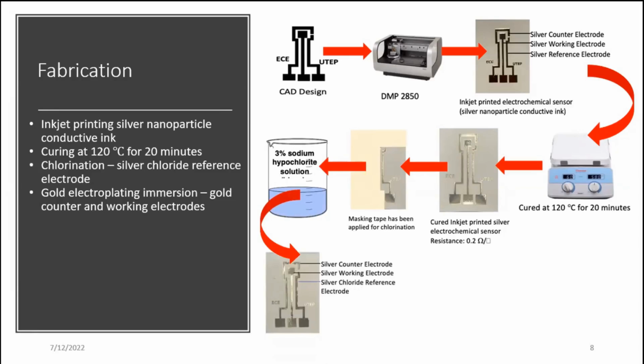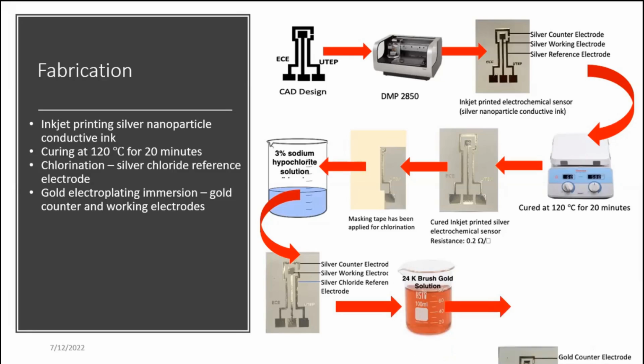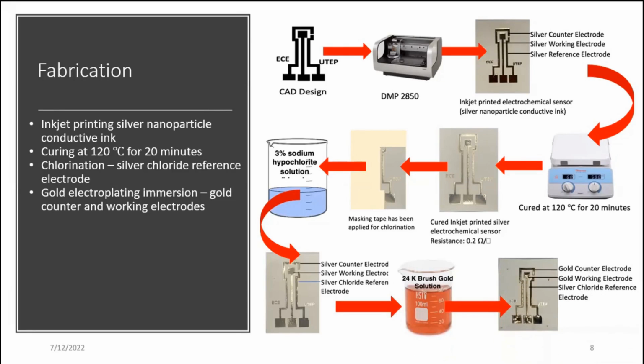And after that, here I want to note one more thing. The reason for choosing Teslin was it was porous, and it really creates a strong bond between the inks and the substrate, which is evident here because we put a masking tape on the working and counter electrode, and we pulled off the masking tape, but adhesion was strong enough that it didn't do any damage to the working and counter electrode. After that, we use the gold electroplating technology. Again, to make it cheaper, we use silver ink, but now we are gold plating it. And finally, here is our gold working and counter electrode and silver chloride reference electrode.